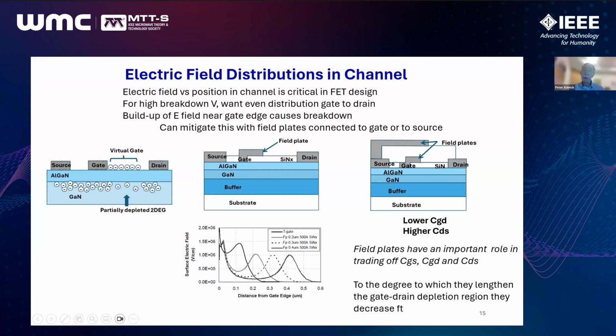This can be mitigated to a considerable extent by the use of field plates that are connected to the gate, or perhaps having a field plate connected to the source. These change the overall pattern of the electric field in this region, as shown here for calculations with different lengths, and they decrease the electric field at the edge of the gate and distribute it over a greater distance. So this is a very important characteristic of the FET. The field plates are good to extend the breakdown.